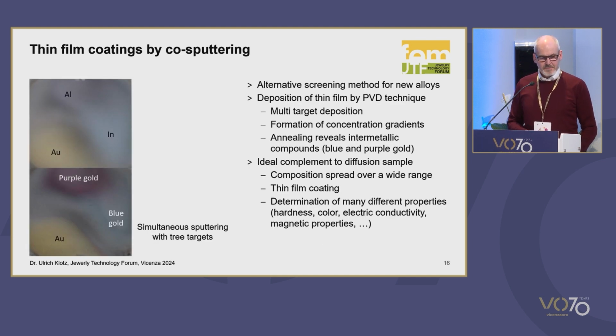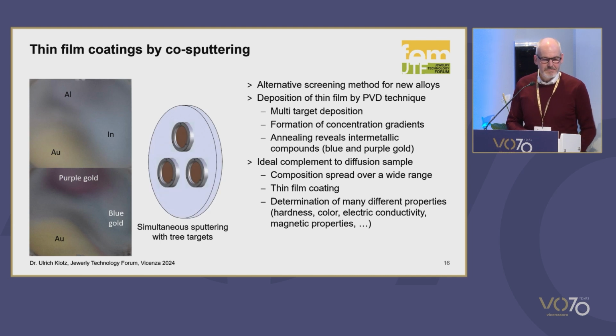Another technique, this is a very old example I found from Jörg Fischer-Bühner's work. This is done, there is a diagram missing here. This was obtained by sputtering technique. So the picture here is showing a glass plate, maybe like 20 times 20 centimeter. And then we used sputtering technique to deposit alloying elements on this glass plate. And we used 3 different alloying elements: aluminium, indium, and gold.